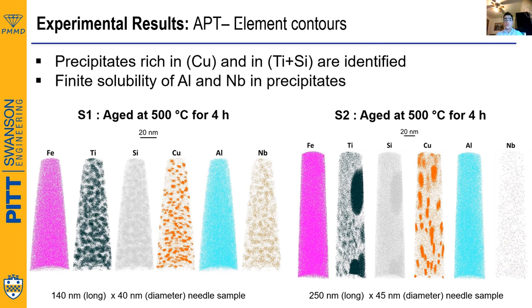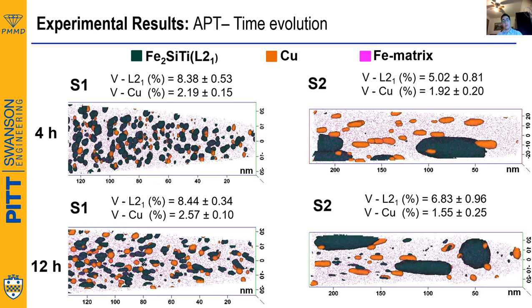So evaluating the aged microstructure evolution in time with APT, we can observe that the volume fraction and size of precipitates does not change much between the 4 and the 12-hour aged samples, confirming then why the peak aging hardness remains constant even after long aging times.